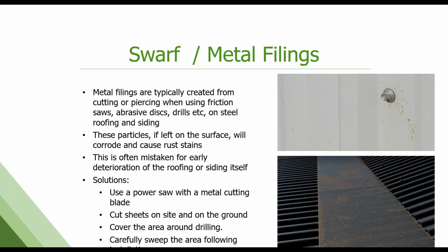So our swarf we talked about, these are metal filings that get left over from drilling and cutting on the job site. There are a lot of technical bulletins on this and how to avoid it, how to clean it up. And this is really on the installer, right? First of all, you should be cutting and drilling away from other metal panels, clean them, and then install them. But if they're left on the surface, you do get these red stains. And it always comes in as a claim of, hey, my roof is brand new and it's already corroding. Well, it's not corroding, it's something on the surface that corroded and then left a red stain, which is very, very hard to remove after the fact, almost impossible actually. So got to cut properly, got to clean up afterwards. Next slide.